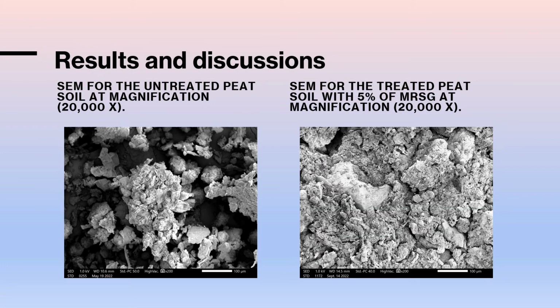These are the microstructures of untreated and treated peat under the same magnification condition. We can see the untreated particles have a fragmented structure that contains visible voids and pores, whereas the treated particles have small pores due to interaction between peat and MRSG, reorganization, and increase in interparticle force.